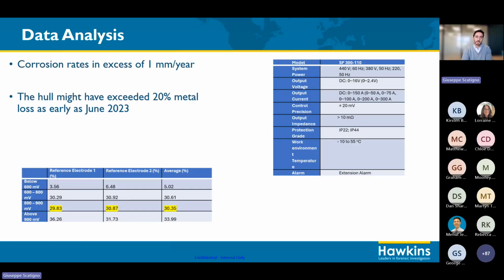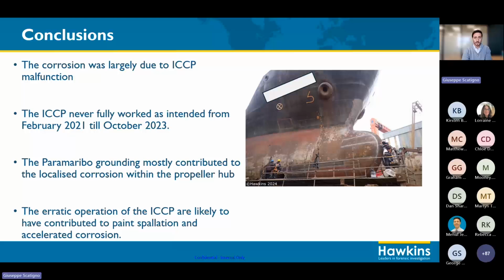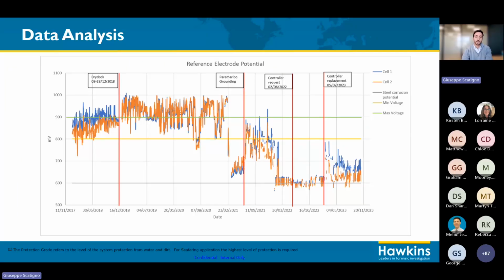So by looking at the data, at the thickness measurement carried out on site by myself and by the surveyor before me, I was effectively able to understand that the corrosion suffered by the hull of this oil tanker, chemical tanker, was to be associated by about 80% with the ICCP malfunction that you could see in this graph, where we have largely erratic behavior of the current, which suggests that we do not have a normal back feed system, but we had effectively most likely manual intervention from the crew that was trying to rectify loss of current by dialing up the system, possibly without fully understanding that really high voltage and current is not necessarily the friend of the hull.